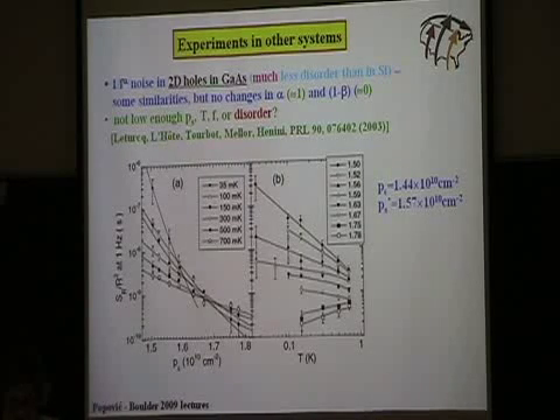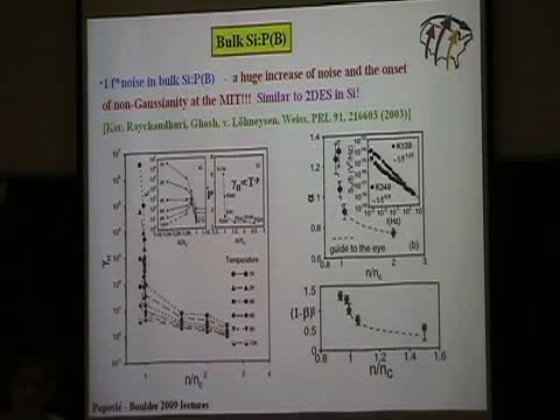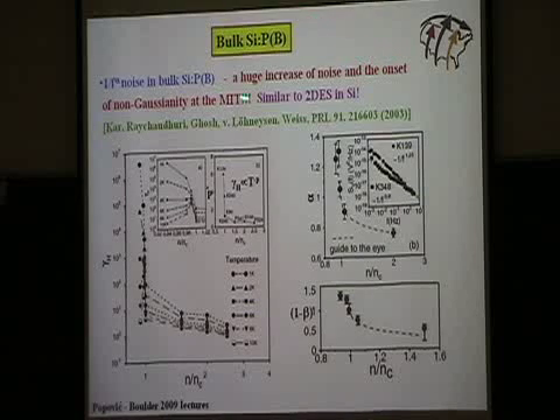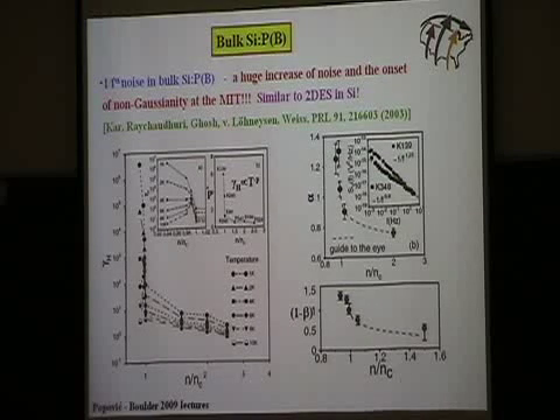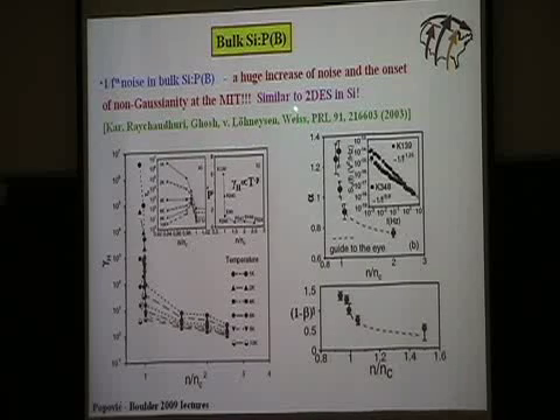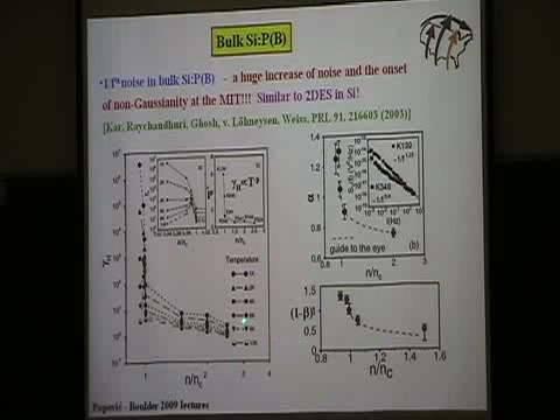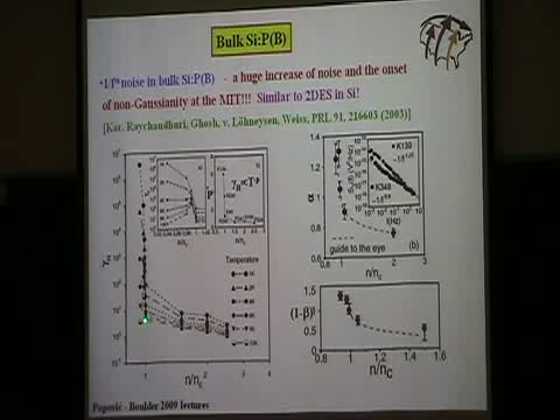One day. So now this is the most exciting to me because we are back to that doped silicon that I started my first lecture with, that has been studied like forever. And after our noise work, these people decided to look at noise in phosphorus and boron doped silicon. And what they found is that, yes, as you approach the critical density for the metal-insulator transition, the magnitude of the noise goes up many orders of magnitude.